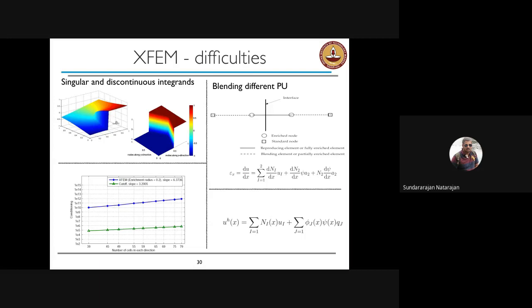The other difficulty is that the conditioning number of XFEM grows exponentially because of the addition of enrichment functions. So care has to be taken such that the functions that we add to the finite element basis are not linearly dependent on the standard finite element basis functions. If they are linearly dependent, we end up with a linearly dependent system, and then your conditioning number goes up, and you will not be able to solve the system. And lastly, since we are adding additional functions, we have additional unknowns. The price to pay here is that we would have to solve an enlarged system as opposed to just solving for the standard degrees of freedom. But again, there is a trade-off when compared to the finite element method, which we'll see in some of the examples where conventional finite element method breaks down, whereas XFEM has a clear advantage.